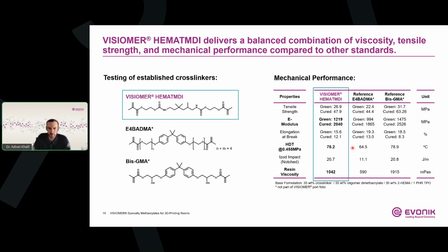Furthermore, the HEMA-TMDI delivers a rather good toughness, as reflected by the Izod impact strength in this case, and a comparatively high elongation at break. This behavior is consistent with the urethane containing molecular structure of the HEMA-TMDI. As I mentioned before, the urethane linkages introduce strong intermolecular interactions while also enabling better stress dissipation within the network. So the resulting formulation is less brittle than